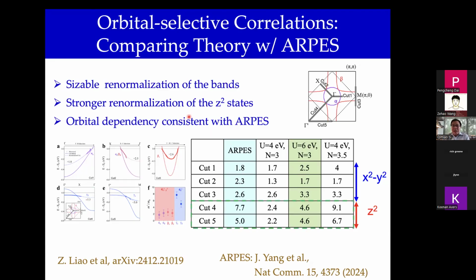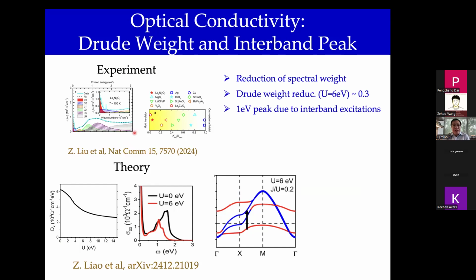So this is the single particle spectrum. We've come back also to look at a bit more details of the optical conductivity, the reduction of the spectral weight in our calculation. We also find, in a reasonable interaction range, that the calculated Drude weight in the presence of interaction is about 30% of the non-interacting result. In experiment, the precise value depends on what part of the measured spectrum is lumped into the Drude part, but by and large, it's even stronger. So maybe there are some details that are still missing in the model, but at least trend-wise, the system is not weakly correlated.